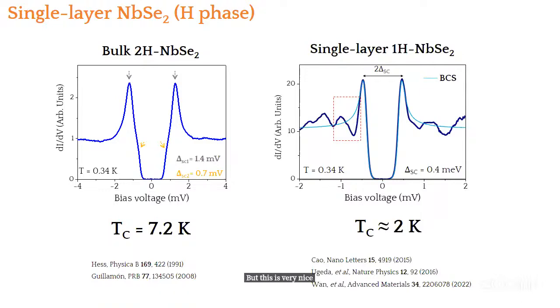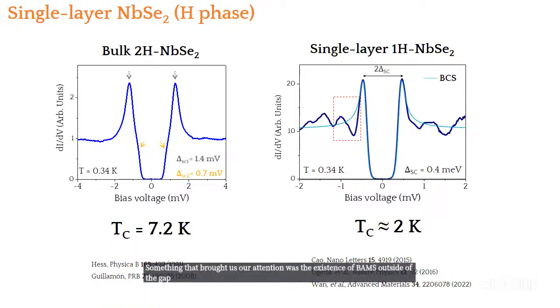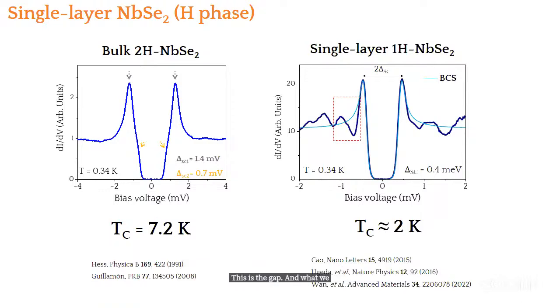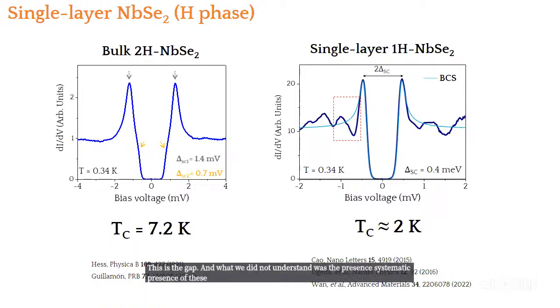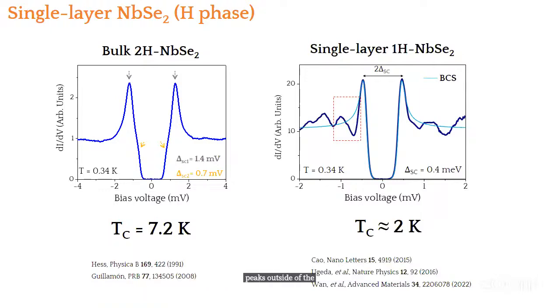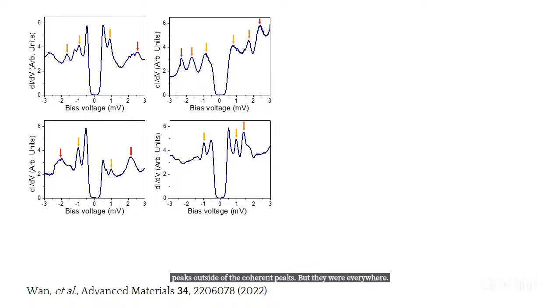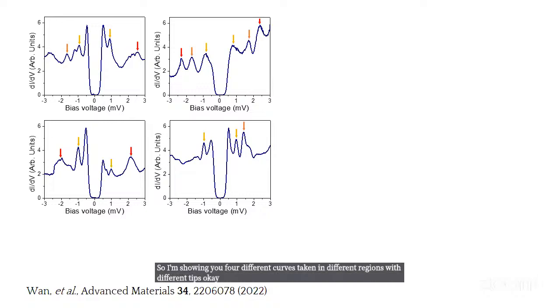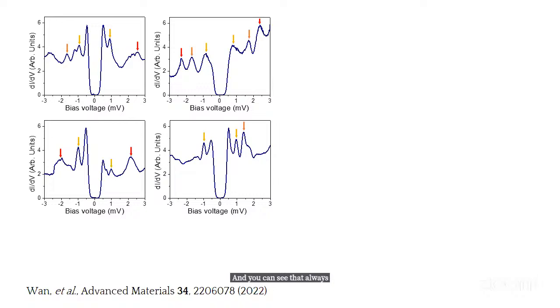But this is very nice because I will introduce you here. So by the time we were looking at this gap, something that brought our attention was the existence of bumps outside of the gap. Okay, so these are the coherence peaks. This is the gap. And what we did not understand was the systematic presence of these peaks outside of the coherence peaks, but they were everywhere. So I'm showing you 4 different curves taken in different regions with different tips, okay? And you can see that always around the superconducting gap, there are these peaks at both occupied states and unoccupied states.